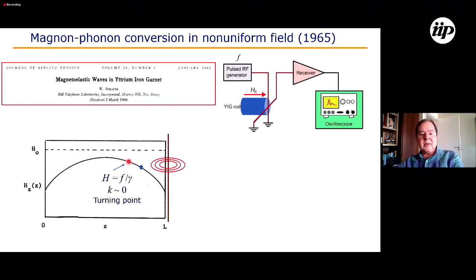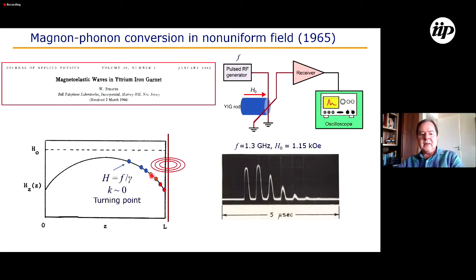And then when there is a pulse, a spin wave is excited here, and then it propagates in the magnetic field. But since the magnetic field is decreasing, at one point, the magnon becomes a phonon. This is because the dispersion relation falls, and then it becomes a phonon. And Strauss observed several echoes. This is the launching pulse, and these are the several echoes, because when the phonon pulse reaches the surface, which is optically polished, it is reflected, and then it goes back to this point, becomes a magnon again, and it does this until it decays away due to the damping. So this was the very nice demonstration made by Strauss.